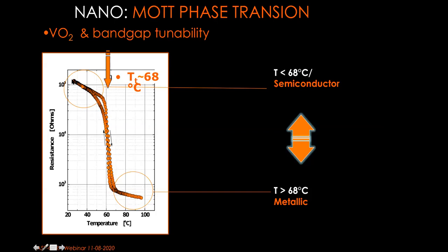It shows you a thin film of VO2 at a temperature lower than 68 degrees Celsius. It's highly resistive. And if you heat it above 68, it becomes metallic. Low resistive, high resistive. Metallic, semiconductor or an insulator. Transparent IR, reflecting IR. That's what it means.